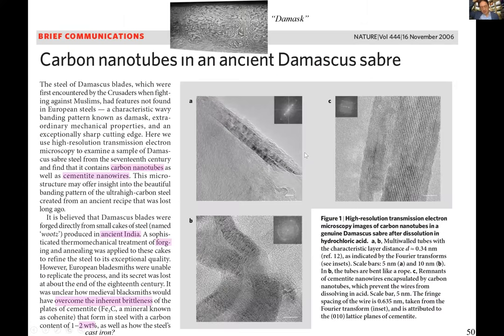So this actually is very interesting because in this ancient Damascus saber, this is actually steel that came from India, but later due to the Mongolian invasion, which cut the trade route, now nobody knows how to make that Indian steel anymore. But when people put it under the TEM, they found microscopically, there are actually these cementite nanowires. That's not very surprising, but there are actually carbon nanotubes also in this ancient steel.